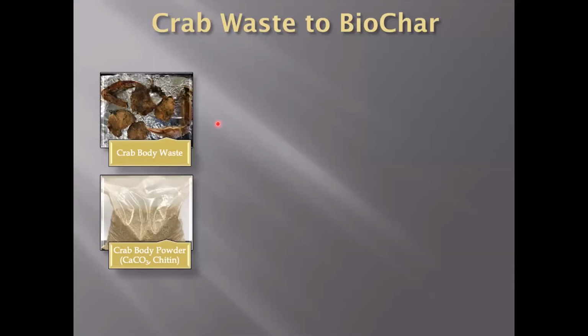And so this is truly the bottleneck of the whole project, because the drying process is expensive. We are really interested in trying to come up with unique ways that we can dry the crab that may be less energy intensive, but currently we use electric heat just as a convenient way to remove the water. So the total conversion of the crab, from the frozen crab to dried crab, is about 32% by weight. So we lose about 68% water mass when we dry the crab.